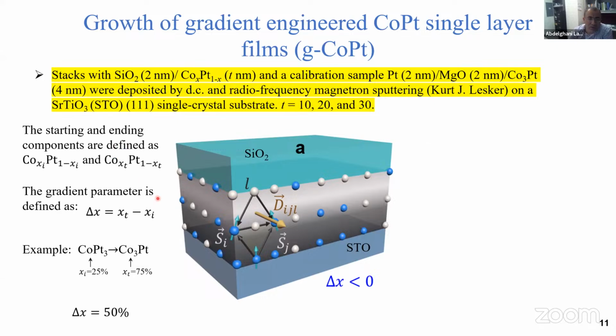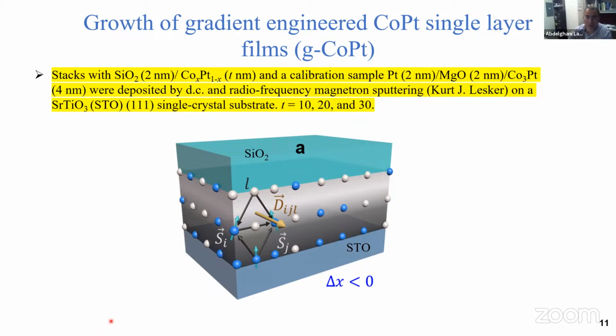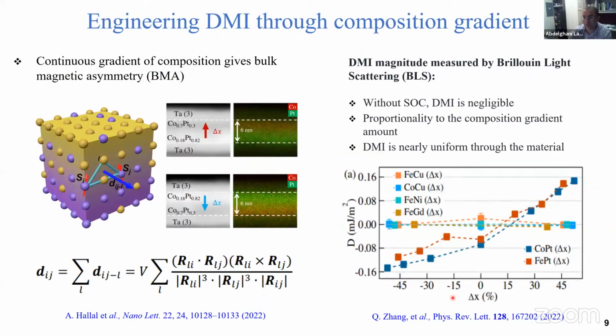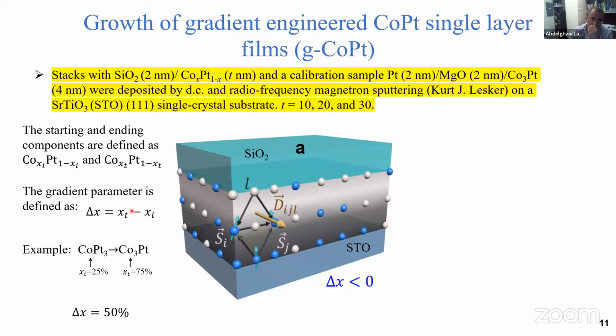Now, if I want to define exactly what we mean when we say delta x, for example 50%, it goes back to here, how we define the gradient content. In this case, the starting and the ending can be defined like here, and the gradient parameter is just the content of the film, in this case cobalt, from the upper layer to the lower layer. For example, if we are studying cobalt platinum 3 and we go to cobalt 3 platinum, the initial content is 25% and you go to the final content of 75%. So delta x is 50%.